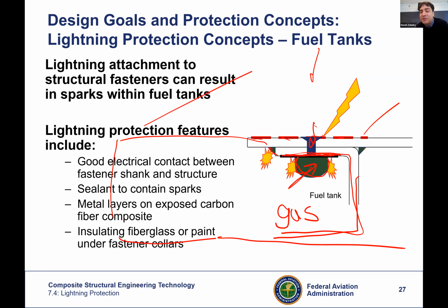Every corner that you can find, you will do that. You will put this putty material, which is like epoxy with some additives, and it protects those surfaces. So what are you protecting? Sparks. You don't want to have any metallic area with gaps around it. If there's metal conductivity and gap, there's a spark. And then there's fuel vapor that, some of it still remains, even with inert nitrogen inside. So that will create fire.